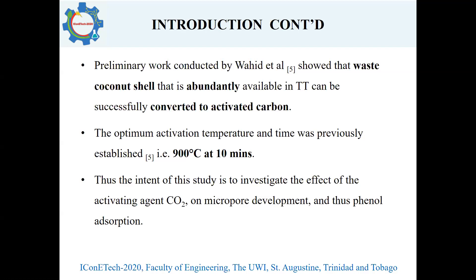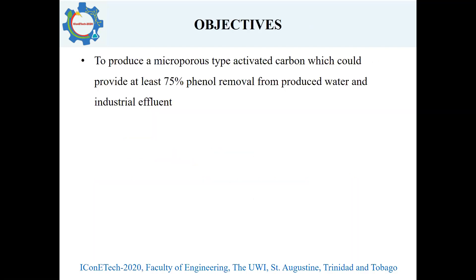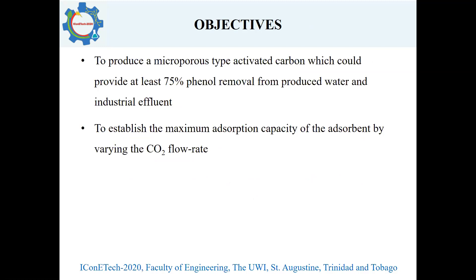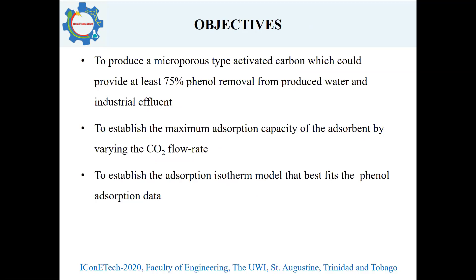Therefore, with ongoing process optimization, the intent of this particular study is to investigate the effect of the activating agent — which is carbon dioxide — on the development of the micropores and therefore enhanced phenol adsorption. Besides aiming to produce a microporous activated carbon which could remove at least 75% phenol from the produced water, we varied the carbon dioxide flow rate to establish maximum adsorption capacity of the adsorbent, and also aimed to establish the appropriate adsorption isotherm model that best fits the phenol adsorption data.